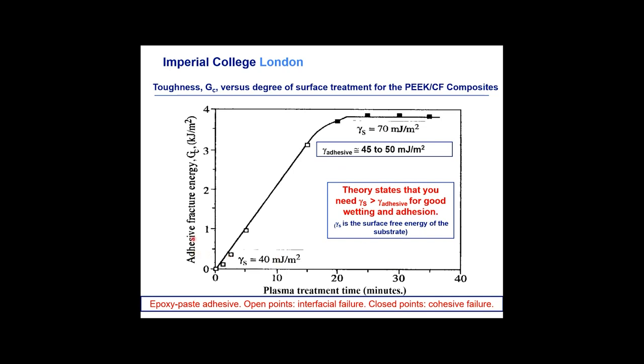We've measured the adhesive fracture energy. Now this is the toughness of the joint, and the adhesive fracture energy is the energy per unit area required to generate a crack through the adhesive joint. This is shown as a function of the time we've surface treated it for in the plasma. And as you might expect, the more you treat it, the more you tend to build up these polar groups on the surface. With no surface treatment, it's got no measurable toughness at all.